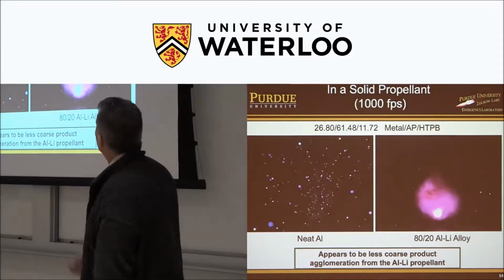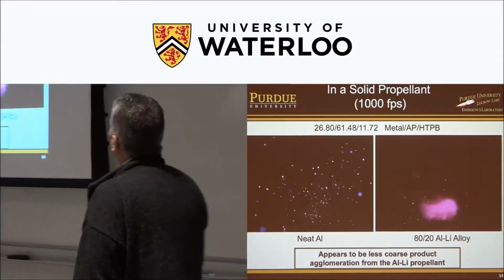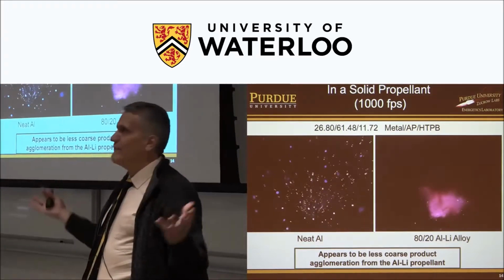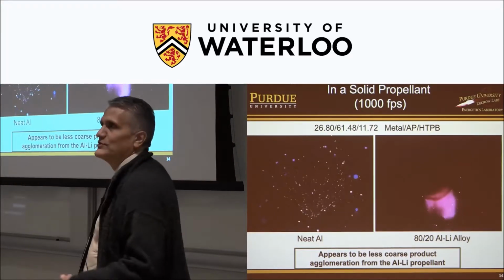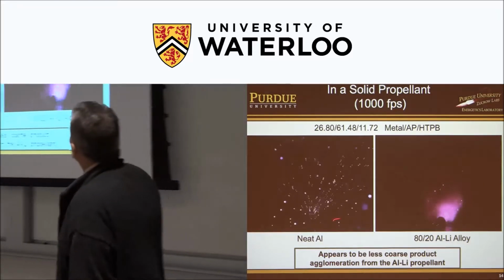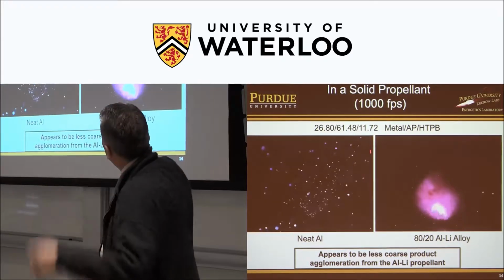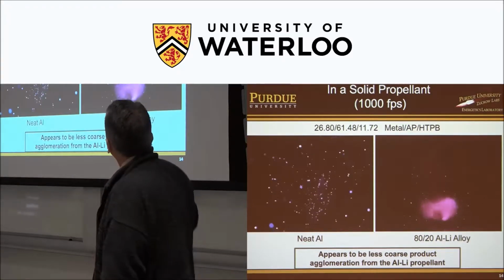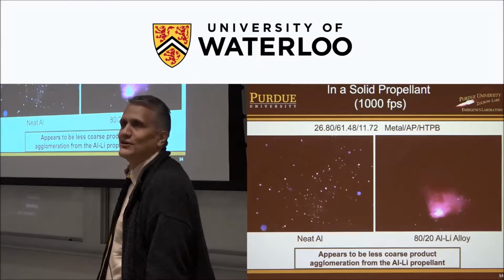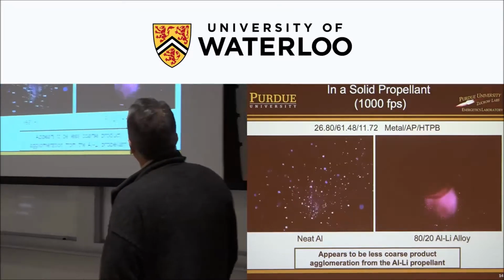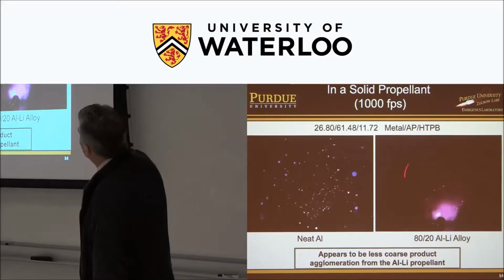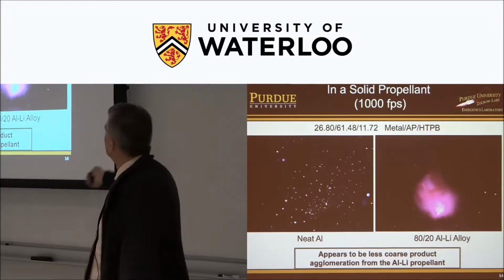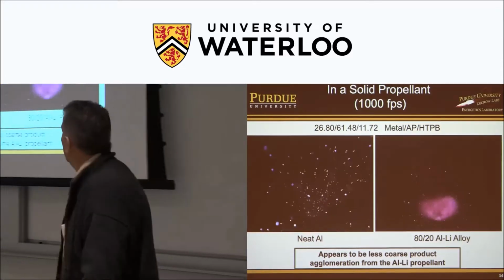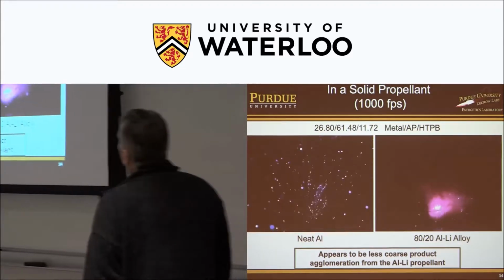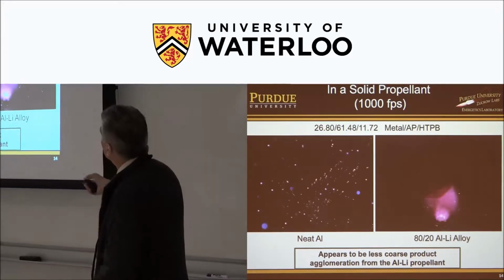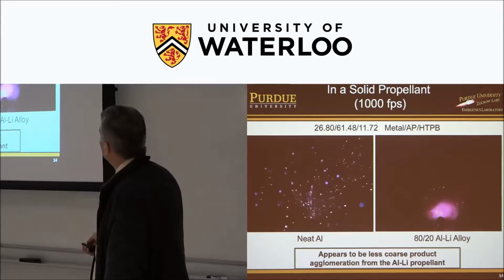So the strand right here is maybe a 1/4 inch. This is high-speed imaging, maybe 1,000 frames per second. Otherwise, it would look like a firework. So those of you who wanted to come to see fireworks, you've seen some fireworks with a high-speed camera. A couple things I notice on this is you see particles burning far away from the strand. Here, the biggest thing that stands out is the color. And that's lithium will burn kind of a magenta. To me, it looks pink. And then look at all the dark space. What does that mean? Those particles are pretty much consumed and done before they move very far downstream. And also it seems to be kind of exploding in an interesting way.